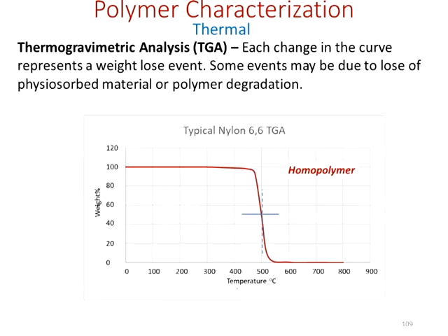So basically this curve shows nylon 6,6 shows one drop. That's how you know you got nylon 6,6. That's its TGA. If it shows anything different, you got a problem. Okay, so there's a degradation, and essentially this tells you that this polymer falls apart at 500 degrees C. That's what this tells you.